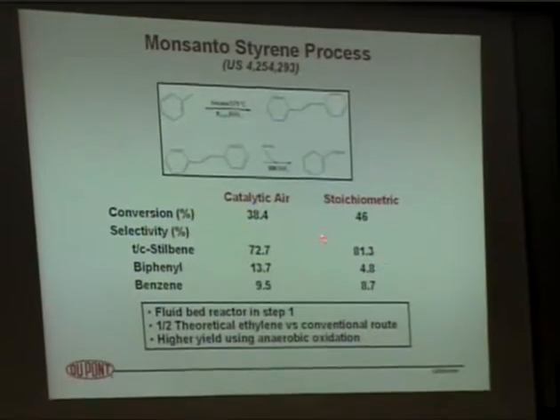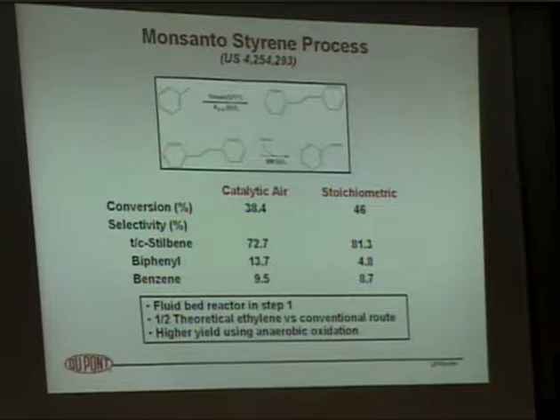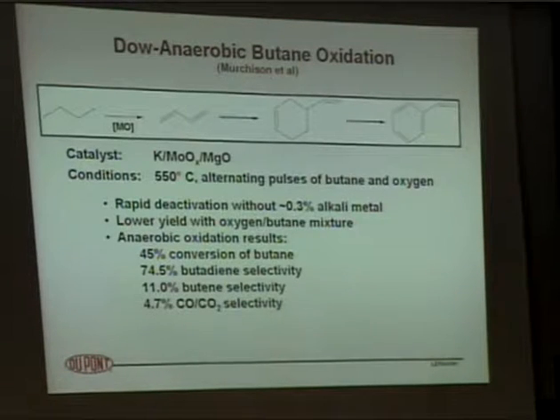When they ran it in the anaerobic, stoichiometric mode with the metal oxide, you can see here that the selectivity was 9 or so percent higher by keeping the oxygen out of that process. This overall reaction is a very nice way to make styrene, uses half of the conventional amount of ethylene, and looked very good. Once again, another technical success, but I guess the situation at Monsanto at the time didn't allow them to go forward. But it was scaled up through the pilot plant stage and worked very well.